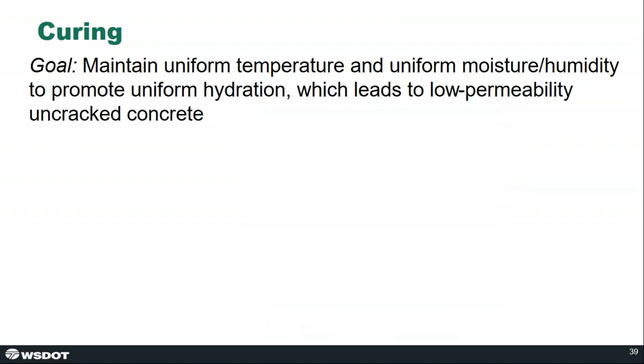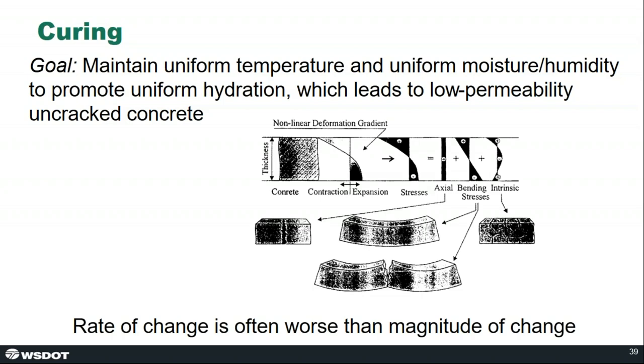So our goal is essentially to maintain uniform temperature and uniform moisture throughout the bridge deck to promote uniform hydration through the section. And this is what gives us low permeability and uncracked concrete. We can't always control all of these variables in the field. Although there's been a lot of changes to concrete mixes over recent years, the way we cure concrete is fairly similar to how we did decades ago.